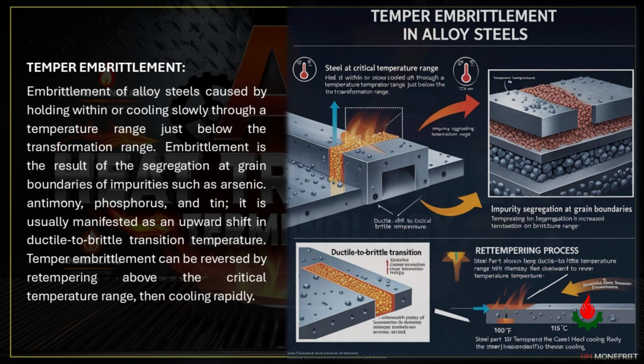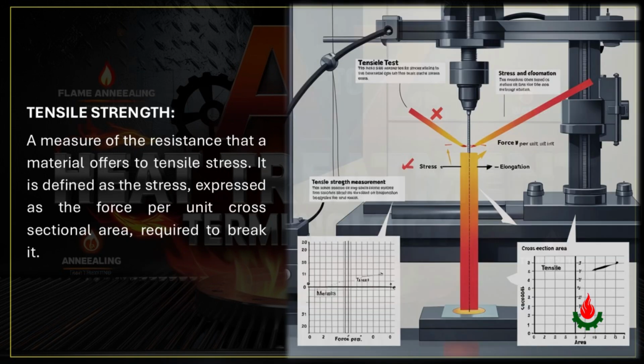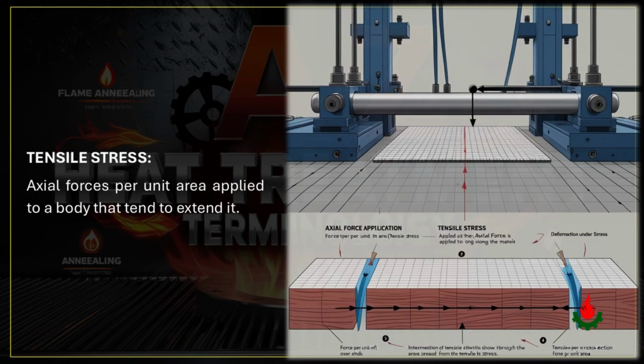Temper embrittlement. Embrittlement of alloy steels caused by holding within or cooling slowly through a temperature range just below the transformation range. Embrittlement is the result of the segregation at grain boundaries of impurities such as arsenic, antimony, phosphorus, and tin. It is usually manifested as an upward shift in ductile to brittle transition temperature. Temper embrittlement can be reversed by retempering above the critical temperature range, then cooling rapidly. Tensile strength. A measure of the resistance that a material offers to tensile stress. It is defined as the stress, expressed as the force per unit cross-sectional area required to break it. Tensile stress. Axial forces per unit area applied to a body that tend to extend it.